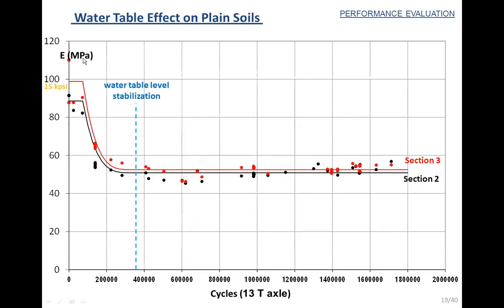This is the modulus. In this picture you can see the modulus of the soil. This modulus represents the material that is below the cement stabilized soil, and you can see the modulus of a medium quality soil. We had around 100 megapascal at the beginning of the test under dry conditions, and then after water table level stabilization we had a modulus around 50 megapascal. So for sure this decrease of the modulus also contributed to the damage of the cement stabilized soil.